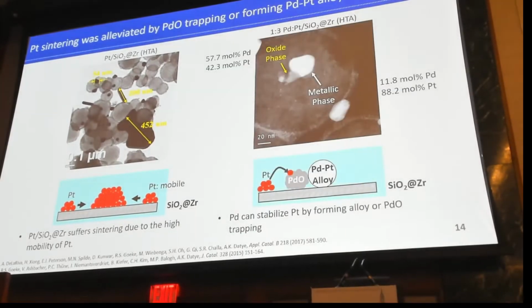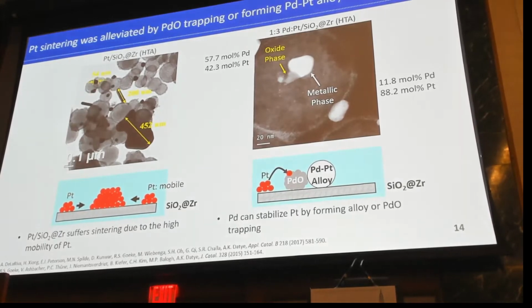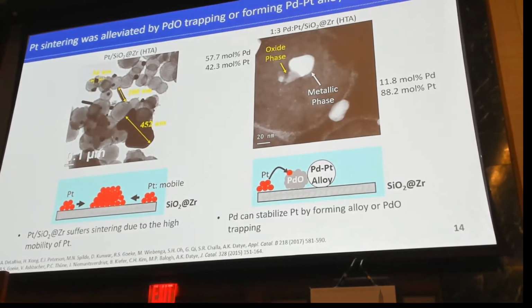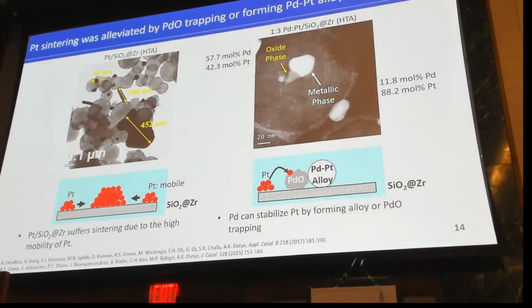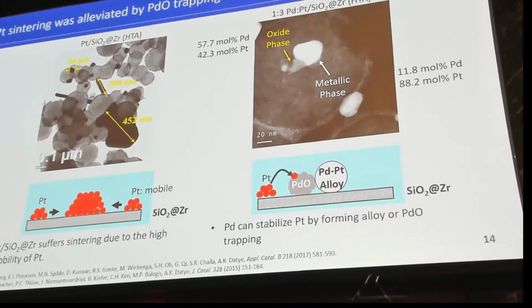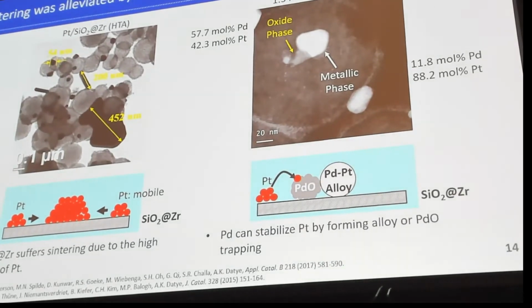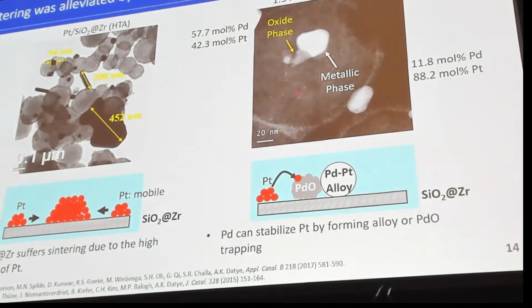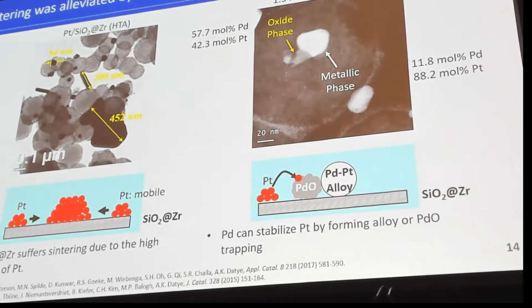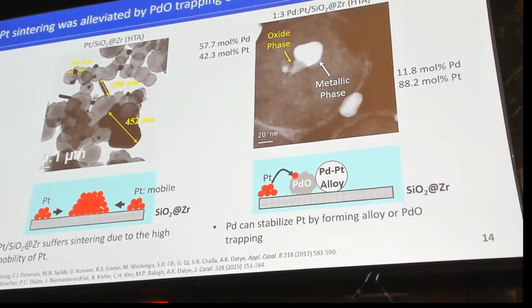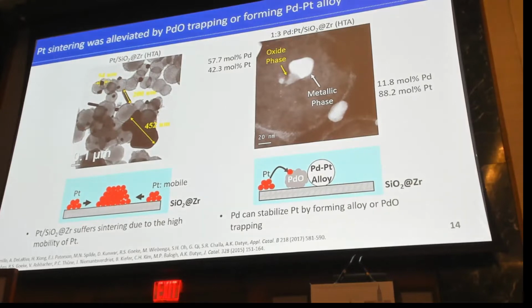So we also did TEM images at the University of New Mexico for the best bimetallic catalyst, which was the 1 to 3 palladium to platinum after hydrothermal aging. And here we saw a couple of small particles dispersed. We also saw particles that are metallic, but more interestingly, we saw particles that look like they are biphasic in nature. Biphasic means that they contain a metallic phase as well as an oxide phase.